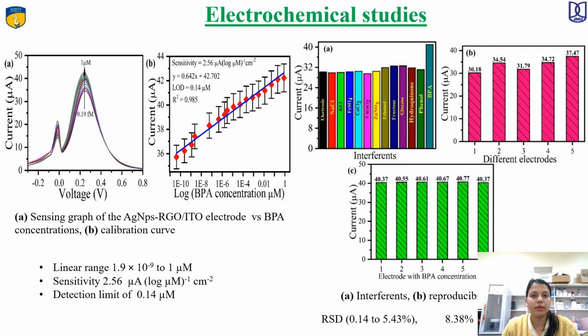The next is the electrochemical response study, in which you can see that there is an increasing trend when we add BPA to the sensor electrode solution, and there is an increasing trend due to the oxidation of BPA on reacting with the surface of the composite electrode, and it gets converted into hydroquinone. And then by plotting the calibration curve, we get the sensing parameters, that is a linear range of 0.19 femtomolar to 1 micromolar, sensitivity of 2.56 microampere, and detection limit of 0.14 micromolar.